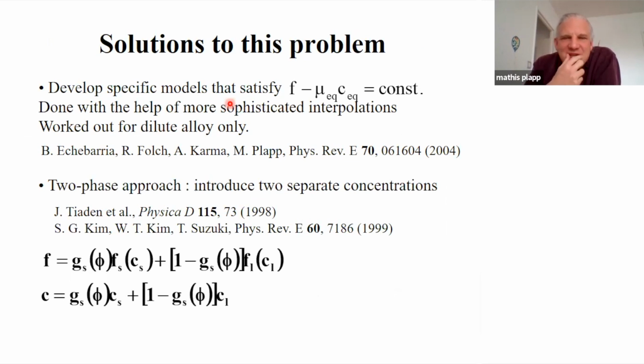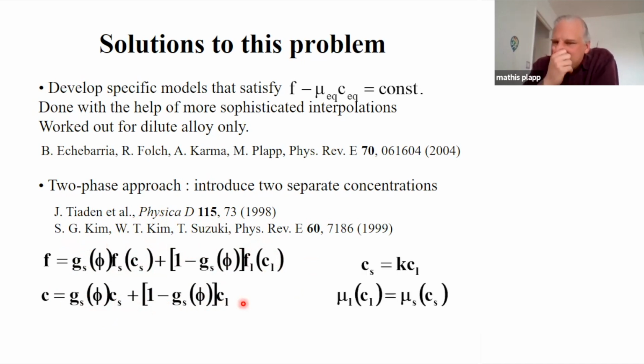Okay, then there was this approach put forward by the people from Aachen in Germany and also quite famous by Kim and Suzuki. They said, okay, if solid and liquid have not the same composition, then let's introduce two composition fields, one for the solid and one for the liquid. Then we can properly write down the interpolation of the free energy with two different concentrations. And the true concentration, we will also get it as an interpolation. But of course, then you have sort of introduced one additional degree of freedom. You need to eliminate this.